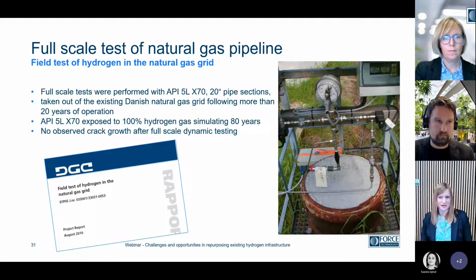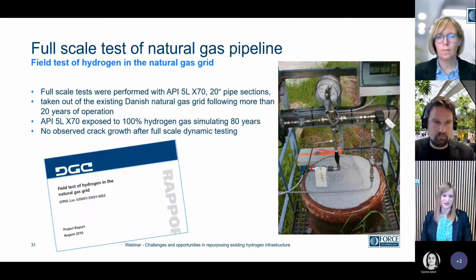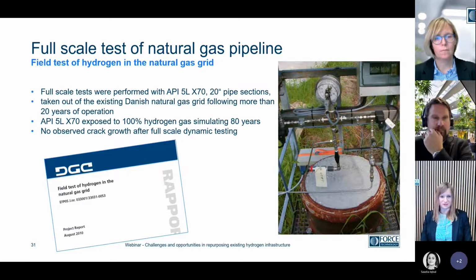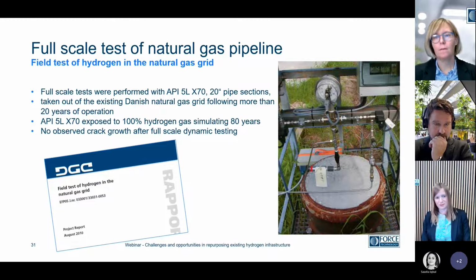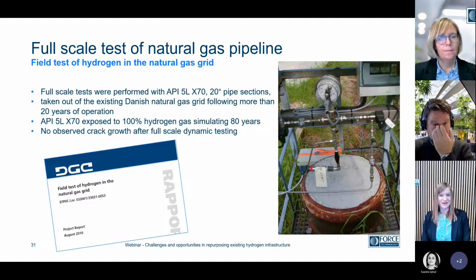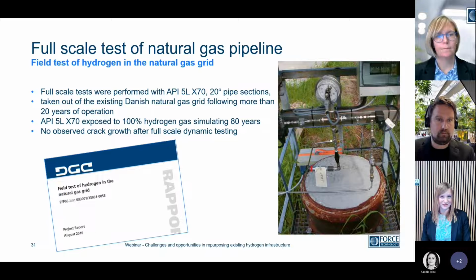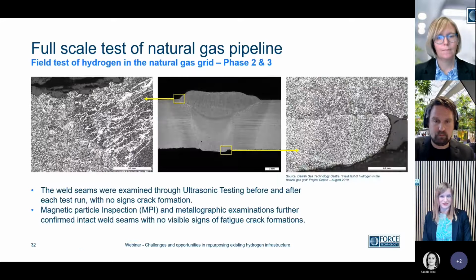And one example of these targeted tests, not just on small-scale specimens, but taking into account residual stress and actual defects, is a full-scale study we performed 10 years back with Danish Gas Technological Center. It was a full section of the Danish gas grid taken out after 20 years of operation. And 100% hydrogen was cycled inside the pipe, simulating 80 years of lifetime, and also subjecting the pipe section to twice the maximum pressure variations of those in the Danish natural gas grid. And exactly the discussion on pressure fluctuation is a big one at the moment. No crack growth was observed after this full-scale dynamic testing.